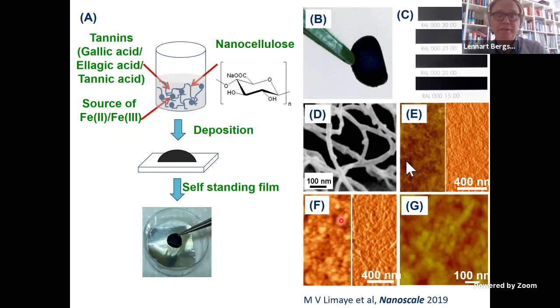We took inspiration from this and tried to devise a patterning method based on iron and tannins. This is an example where we mix tannins like gallic acid, ellagic acid, and tannic acid with an iron source and cellulose nanofibrils.